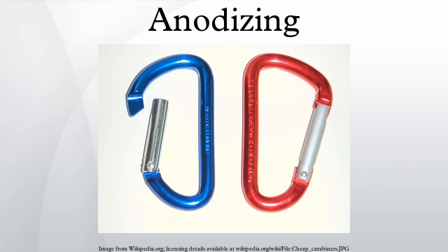Again, the film thickness is dependent on the anodizing voltage and typically ranges from 18 to 23 angstroms per volt depending on electrolyte and temperature. Uses include tantalum capacitors. Dyeing. The most common anodizing processes, for example sulfuric acid on aluminium, produce a porous surface which can accept dyes easily.